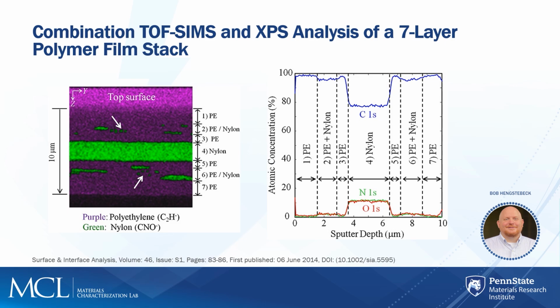But from the XPS standpoint, they did a traditional profile using the GCIB source, and not only could they see the different layers by looking at composition, but they're able to preserve the chemistry and actually have peak fitting using least squares fitting, where they can look at what's polyethylene, what's nylon, what's polyethylene and nylon as you go through the stack. And so they're actually able to very quickly show not only compositionally what's happening, but tell you how much of it would have been polyethylene, how much of it would have been nylon in those mixed layers. That's pretty unique, and it's something we're excited to be able to offer to you.